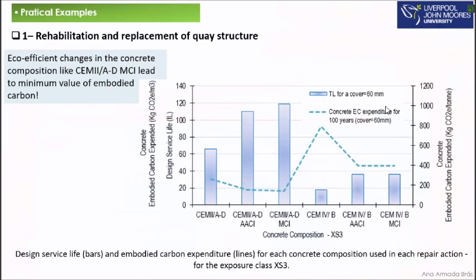So we compared the performance in terms of service life of the concrete compositions. I show as an example one graphic here. You compare the concrete design service life with the embodied carbon expended in kilograms of CO2 equivalent per ton of concrete produced. As you can see, the design service life are the blue bars, and the embodied carbon expenditure are the lines for each concrete composition used in each repair action. The graphic that I show is for an exposure class: the tidal splash zone of the columns.